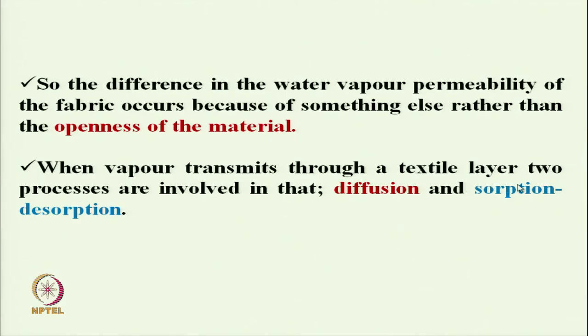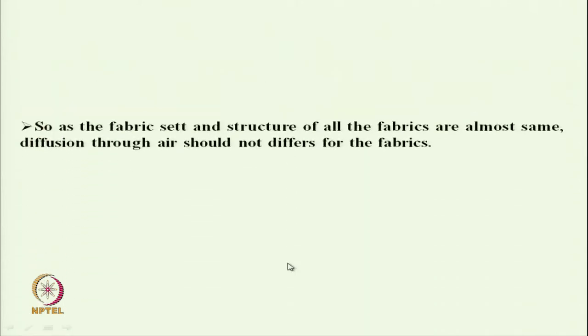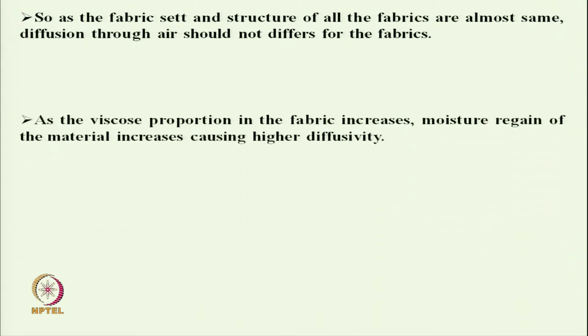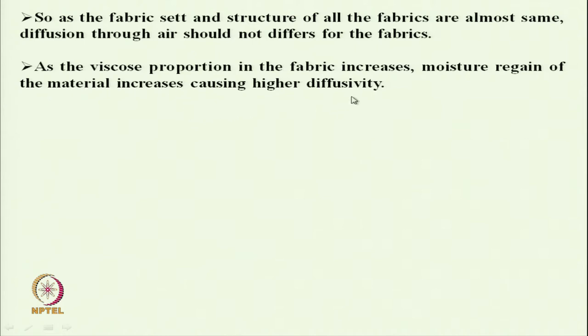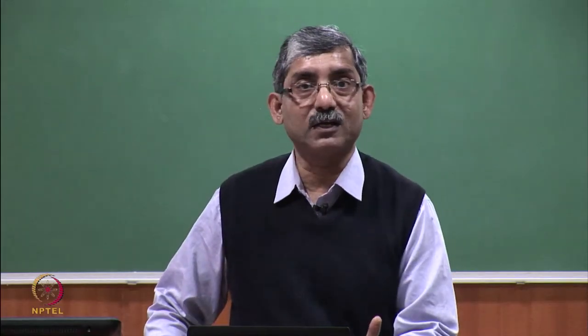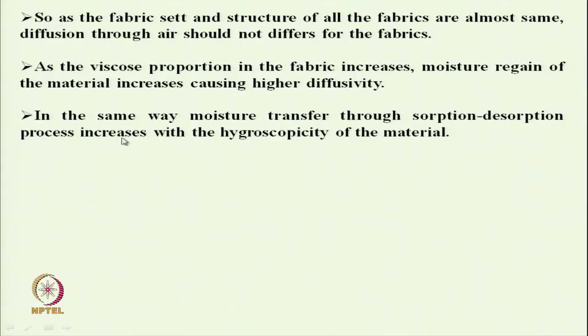When vapor transmits through the textile layer, two processes are involved: diffusion and sorption desorption. As the fabric structure was kept constant, the diffusion was also constant. As the viscose proportion in the fabric increases, the moisture regain of the material increases, causing higher diffusivity. So again, non-Fickian diffusion will also be there. In the same way, moisture transfer through the sorption desorption process increases with the hygroscopicity of the material. So both non-Fickian diffusion and the sorption desorption method of moisture transmission take place here.